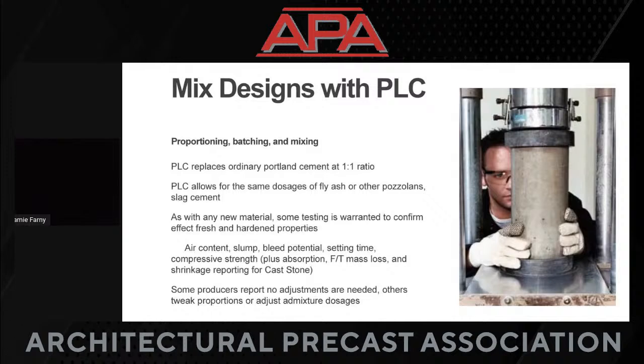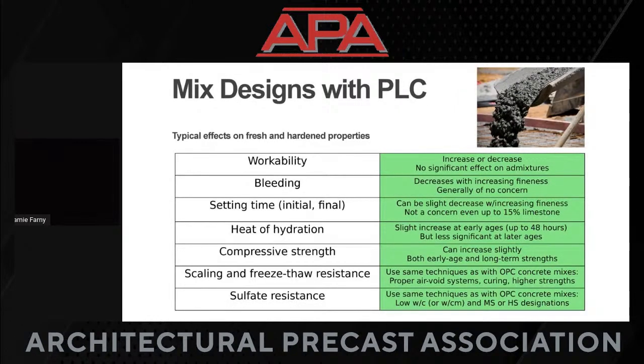We have to check the setting time, both initial and final. We got to look at compressive strength. I did this for a cast stone group not too long ago. In that particular part of the industry, they're very concerned about absorption and freeze-thaw mass loss and shrinkage. So their standard requires either having limits on these or sometimes at least reporting how those things are affected. And what we hear from many parts of the industry, remember this information that you're seeing today is largely focused at ready mix, is that some producers report that they really don't make any adjustment once they do that 1-to-1 swap. Others are saying, I may have to bump up my admixture dosage or bump it down. I'm seeing just a little bit of difference in what I get out of my concrete mixes. So I know how to control with admixture technology.